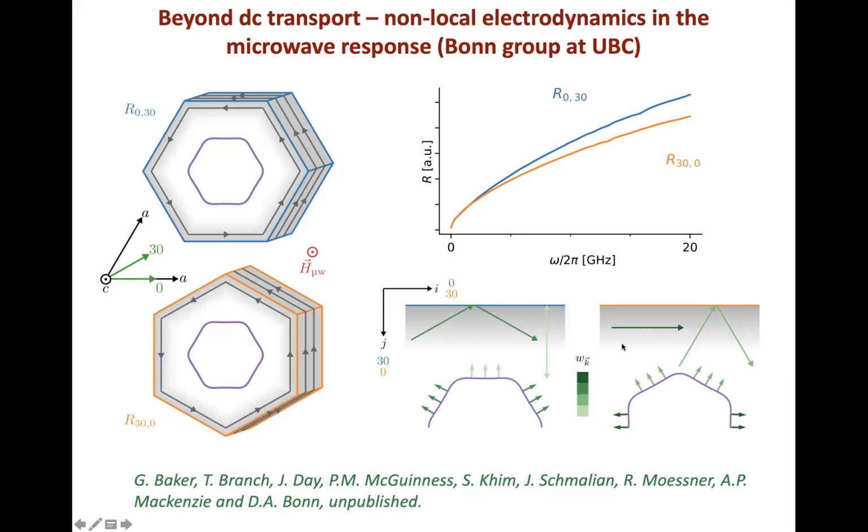And in one of these two orientations, you have something that you never have had before, which is a substantial fraction of your electrons being injected or moving or possessing Fermi velocities which are parallel to the surface being studied. And that is what Graham is doing, along with advice from some of the other theorists in the collaboration. Graham has done a very, very nice model where he can match the key features of the data, at least to a decent accuracy. And that confirms that this special thing of having a substantial subpopulation of electrons moving with Fermi velocities parallel to the surface is the key to understanding these results.